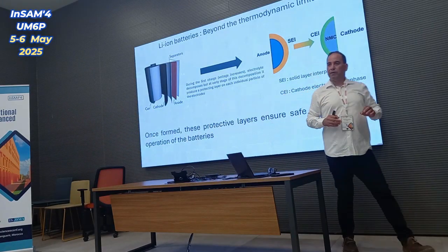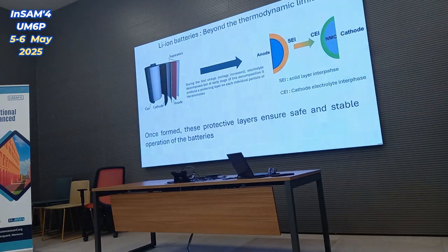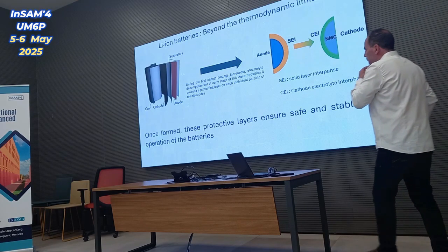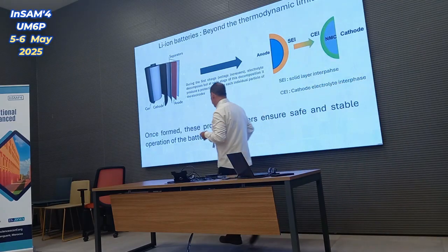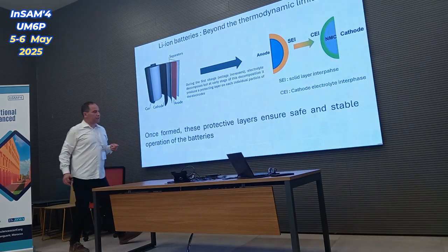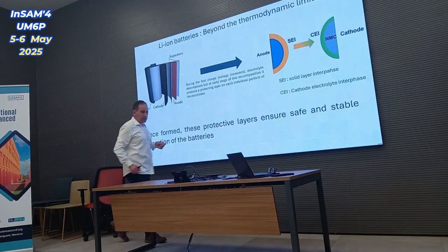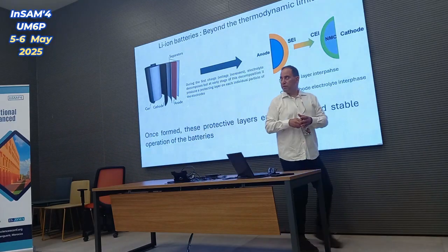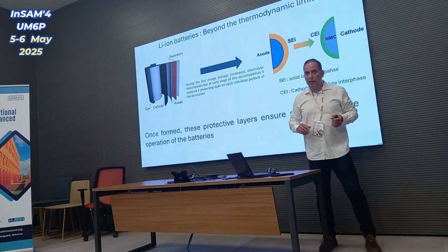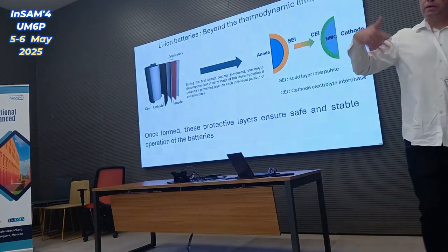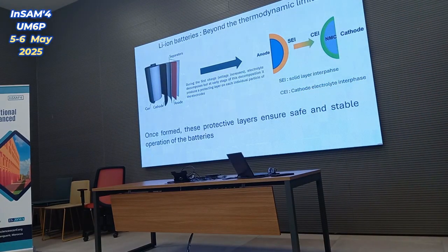And if the coating, this passivation layer, is efficient, then the irreversible reaction during the following cycles will decrease and will stop. Once formed, this protective layer ensures safe and stable operation of the batteries. It's essential, because if we don't form this protective layer, the decomposition of the electrolyte will continue, and we will consume the electrolyte, and we will increase the internal resistance of the battery. So the battery will stop functioning.